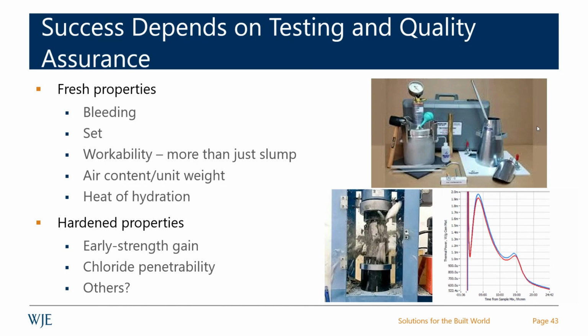Hardened properties of concern. As I mentioned, early strength gain can be a concern with some systems. Chloride penetrability, and I use that terminology specifically in that we often use electrical methods, whether it's ASTM C1202, which is a rapid chloride penetrability test, or resistivity, like bulk resistivity. But sometimes the electrical methods get fooled by the poor system chemistry in some of these systems. So we may need to do more benchmarking where we do chloride ponding to at least then benchmark our electrical methods. And there could be other concerns like shrinkage, for example.